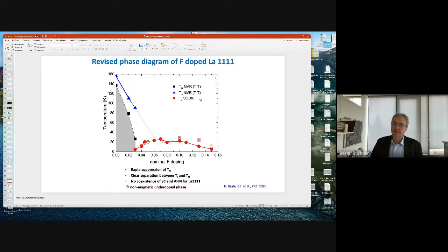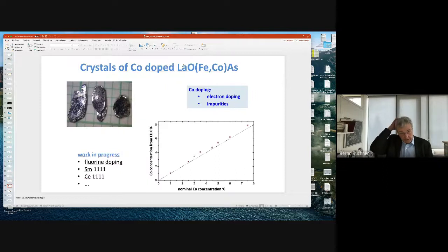But this is on polycrystals where we can do fluorine doping. Unfortunately, even with our technique so far, we can only produce crystals where we dope with cobalt atoms. So we replace iron by cobalt. We know that these also lead to some increase of electron charge carriers, but it also leads to impurities. So it's not the best material. We knew that TC, which we can expect, is much smaller. However, it's a chance for the first time to measure really a series of single crystals on that. And of course, we are currently working in our chemistry part to work on other systems with higher TC and fluorine doping, but it turns out to be very, very difficult.